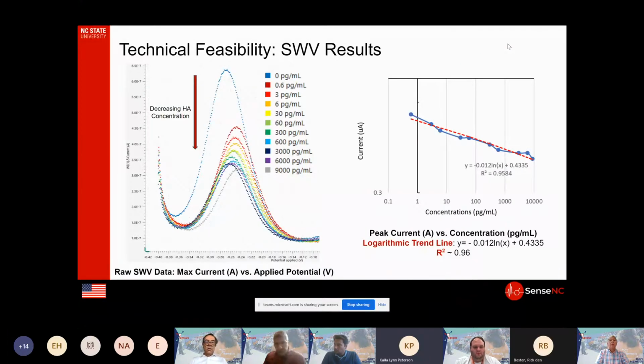Preliminary testing of our Apta sensor exhibited a dose response for hemagglutinin. With increased hemagglutinin concentration, our sensor shows a proportional reduction in peak current. Our Apta sensor was tested in artificial saliva and operated over a dynamic range of 0.6 to 9,000 picograms per milliliter, which is the clinically relevant range. We tested our sensor at both 0 and 120 seconds delay and compared the results. Comparable results were realized for both incubation periods, suggesting our sensor response time will be significantly less than 5 minutes. This is the first example of square wave electrochemical detection for a hemagglutinin Apta sensor.